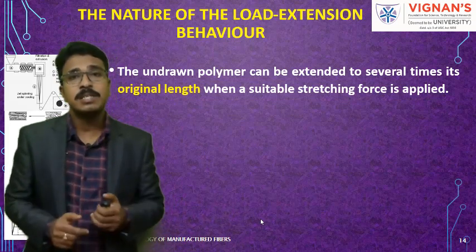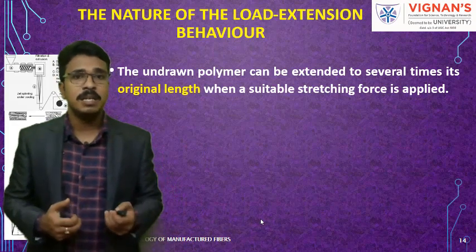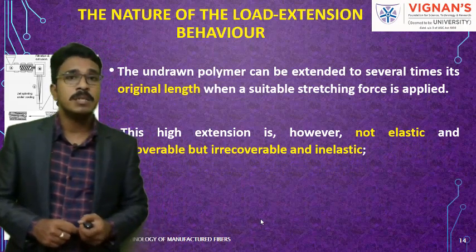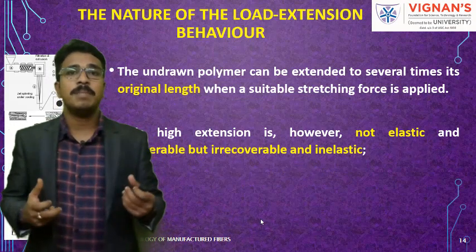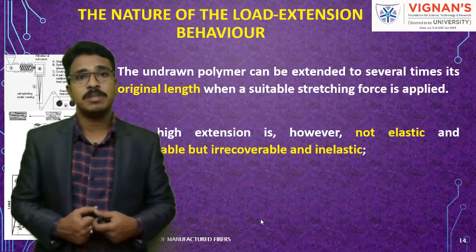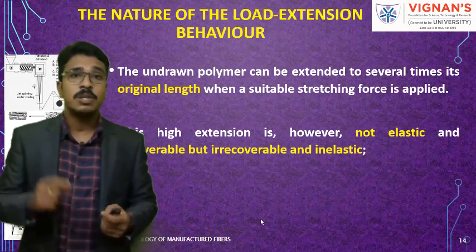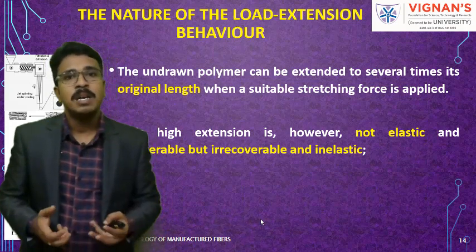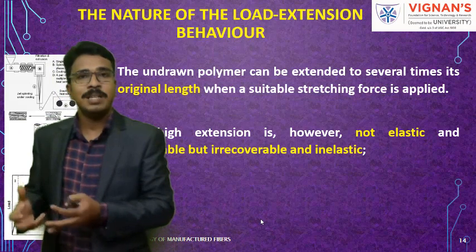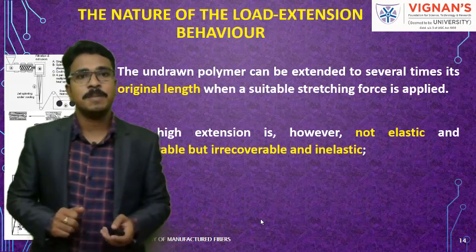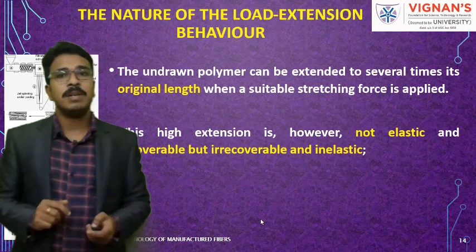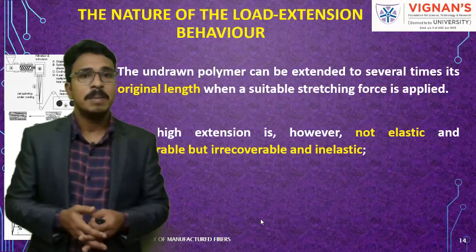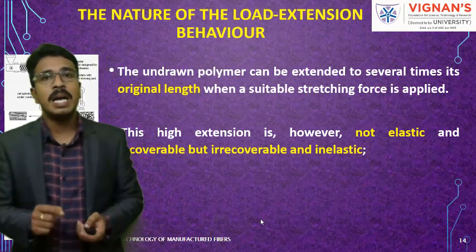It can be extended to several times its original length when a suitable stretching force is applied. When a suitable stretching force is applied, these undrawn filaments can be extended to several times their original length. However, this high extension is not elastic. That means if you remove the load, the filament will not come back to its original state. It is irrecoverable and inelastic.